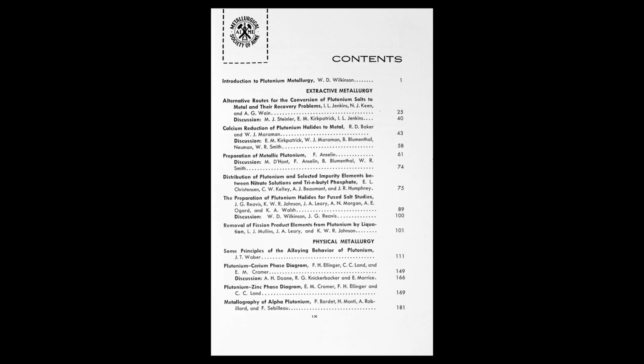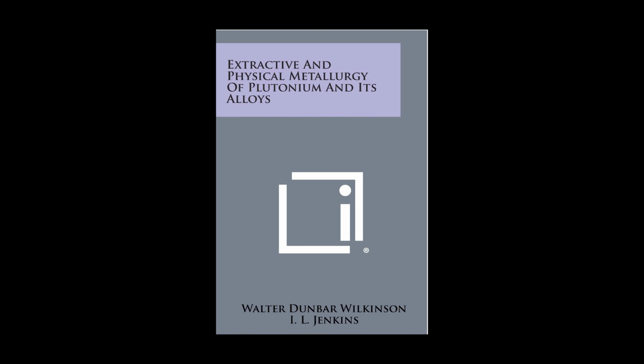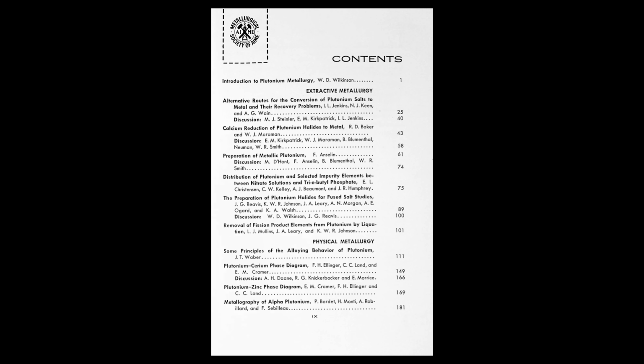The text also brings up something called Darken-Gurry maps. What are those about? Darken-Gurry maps, shown in figures 2 and 3 of that section, are pretty clever graphical tools. They try to predict how much solid solubility you might expect between two metals. Predict solubility? How? They plot elements based on two fundamental properties, atomic size and electronegativity, basically how strongly an atom attracts electrons.